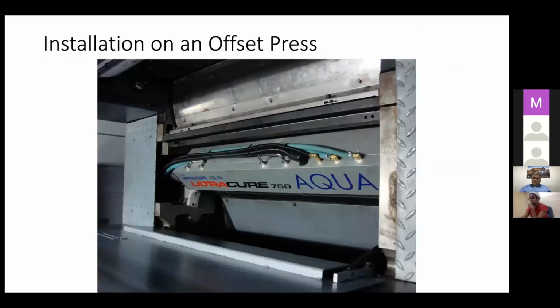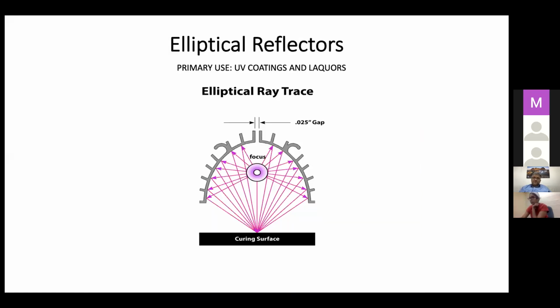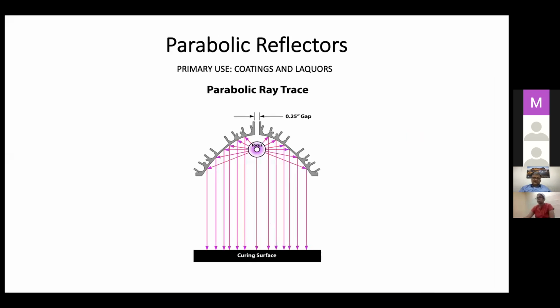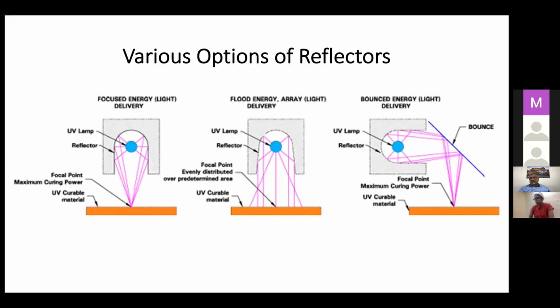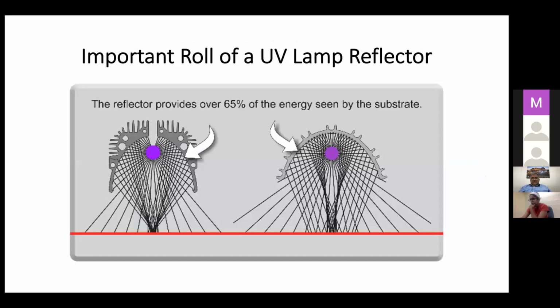This is one of our water-cooled systems, the UltraCure Aqua, installed on a Heidelberg CD74 interdeck UV system. As Ramakrishna has already mentioned, I won't go through this again. So we have elliptical reflectors, parabolic reflectors, and various options to throw the light on the substrate. I do wish to add that the reflector is an integral part of the system, where the reflector is responsible for 65% of the energy seen on the substrate. If we remove the reflector, we will only have about 30 to 35% energy falling on the substrate, which is not enough for curing in any given application. So reflectors are a very, very important part of our system, and it is something we take very seriously.